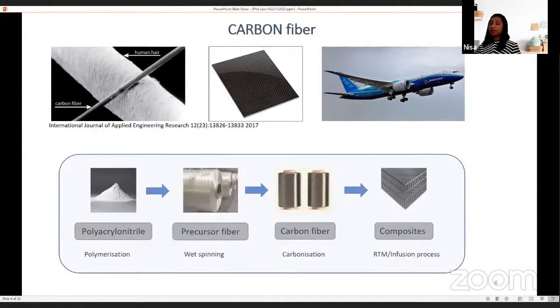So here is a quick representation of carbon fiber production. The starting material for the production of carbon fiber is a synthetic polymer called polyacrylonitrile, or PAN. Currently about 90% of carbon fiber production is from PAN, mainly due to the good carbon yield and its stability. So this PAN undergoes a process called wet spinning. Here we are extruding the polymer into a solvent in a coagulation process, and that's the way it forms a white fiber, or precursor fibers. These precursor fibers, when given a high temperature treatment over 1000 degrees, form carbon fibers. These carbon fibers are later embedded in a polymer matrix to make structural composites.